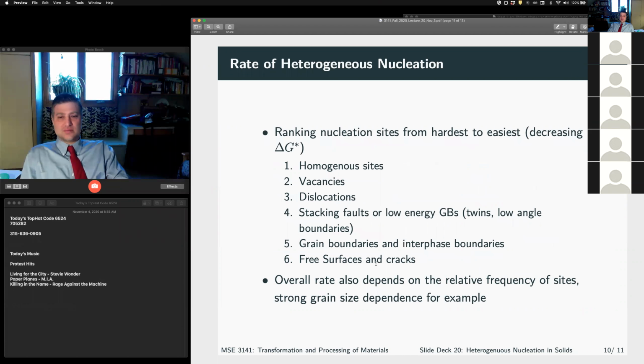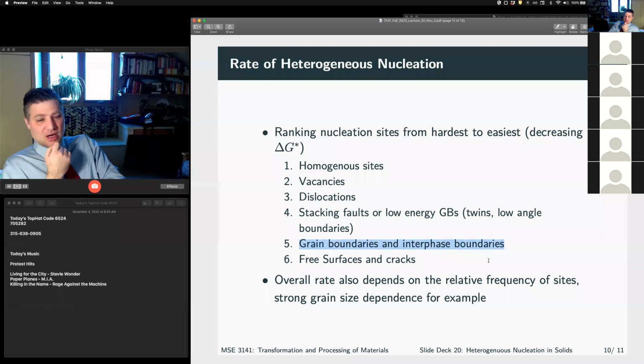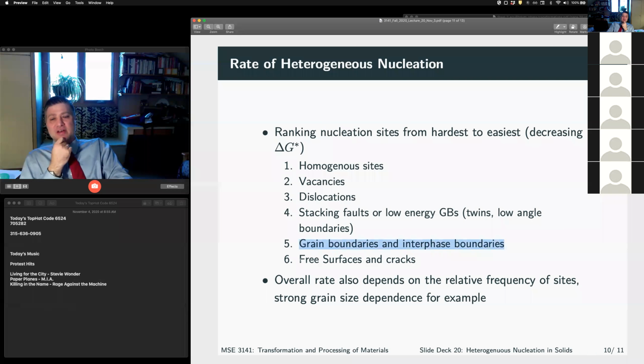right? Okay, so if we rank them from hardest to easiest, right? Homogeneous nucleation is obviously the hardest, then nucleation at vacancies, nucleation at dislocations, nucleation at stacking faults or low energy grain boundaries, nucleation at grain boundaries or other interphase boundaries, and then nucleation at free surfaces.